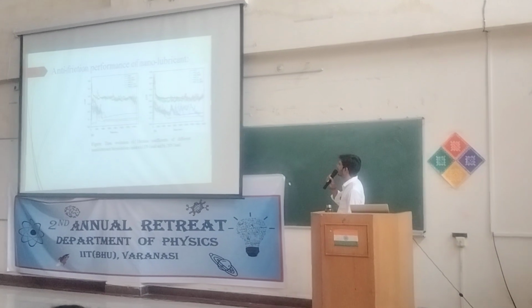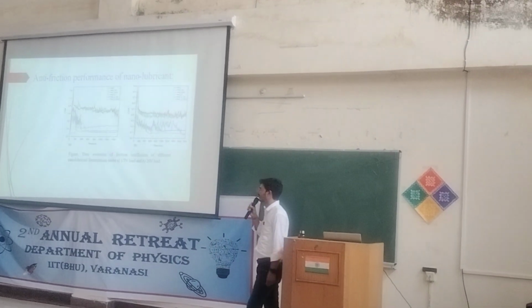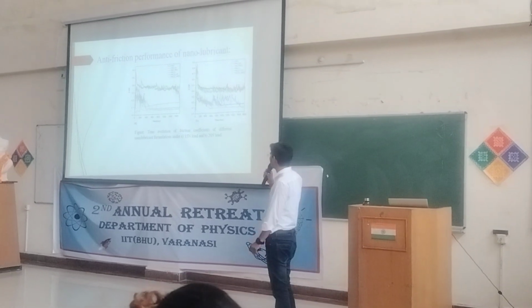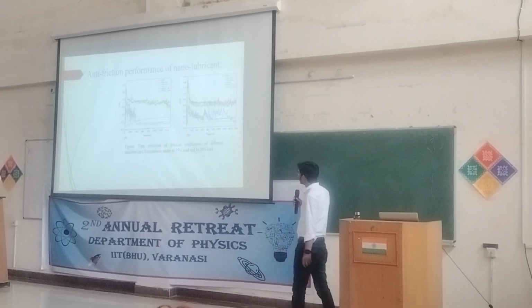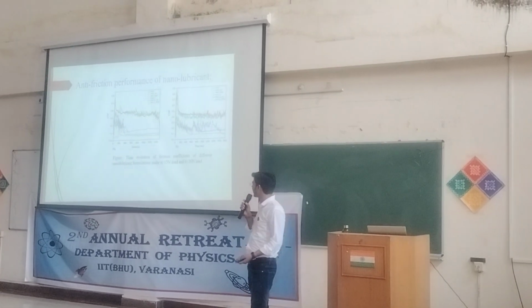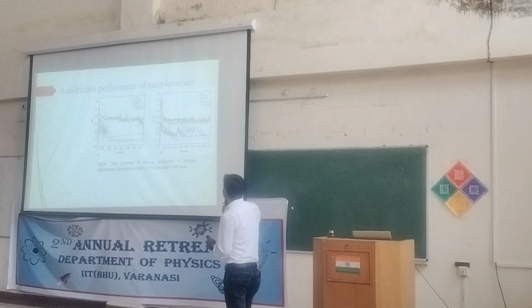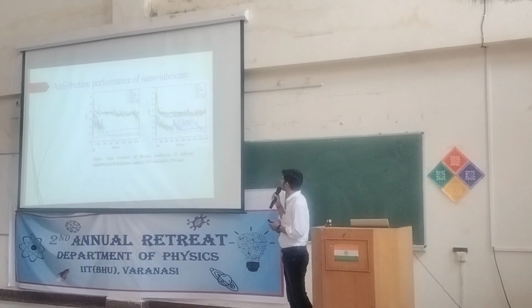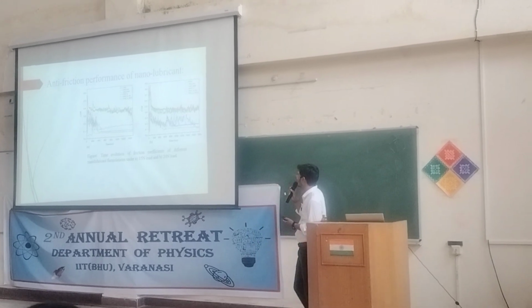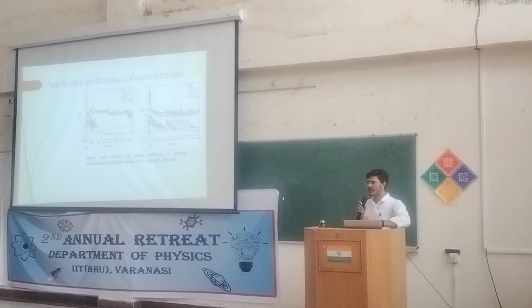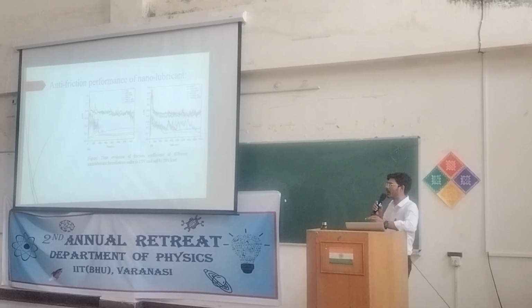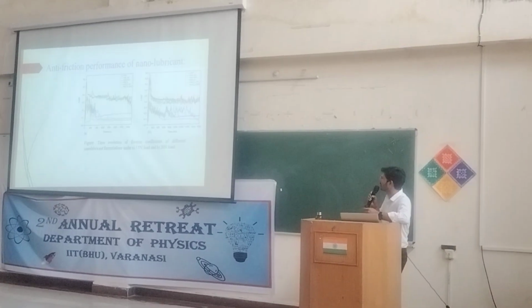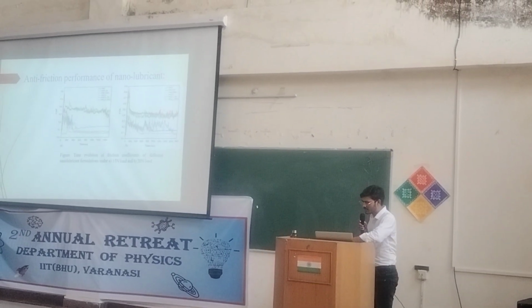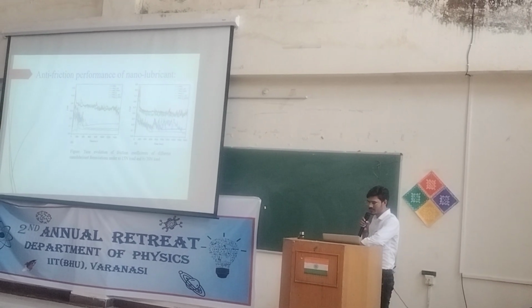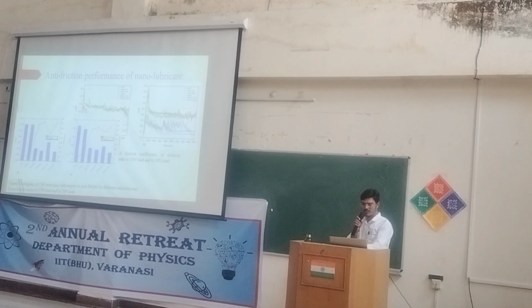In my previous research, this is the anti-friction performance of these nanolubricants, in which I have used polyalphaolefin based synthetic oil, in which I dispersed the graphene oxide functionalized by melamine. In this research, at different loads, I was able to reduce the coefficient of friction by 73% as compared to the base oil, because in a previous study it was found that almost one third of the energy of the fuel is lost in the form of friction. So to overcome this, I was able to reduce the coefficient of friction by 73%. This is the histogram of different formulations.